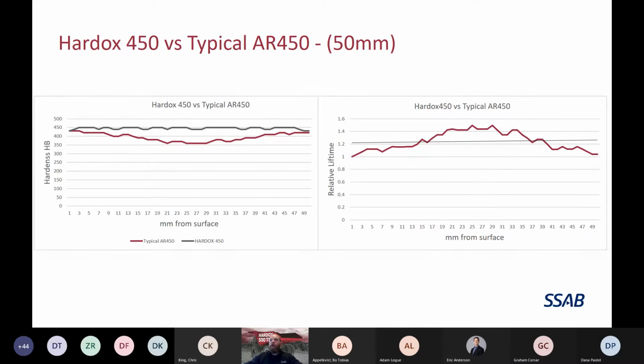And this becomes even greater when you go to something like a 50 millimeter or 2-inch plate. Looking at the graph to the right, the relative lifetime can be a little over 20% improvement just switching to Hardox 450. A lot of people say, well, what's the cheapest price? But with Hardox, we're looking to create value, not just sell you a cheap plate. We're trying to make sure that the plates we sell you will give you good performance, longer lifetimes and much more consistent wear. A lot of mines typically want a regular scheduled maintenance interval, and they don't want unpredictable downtimes.